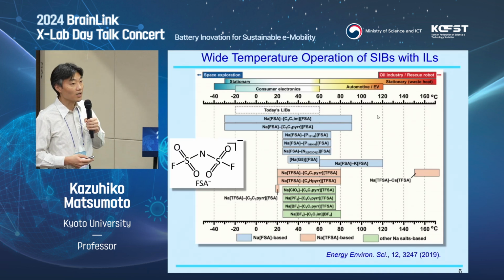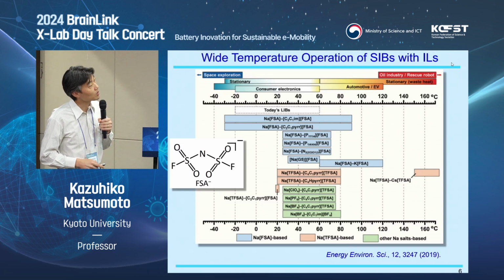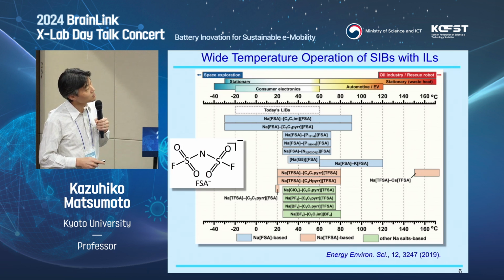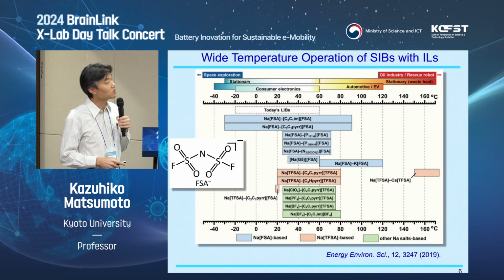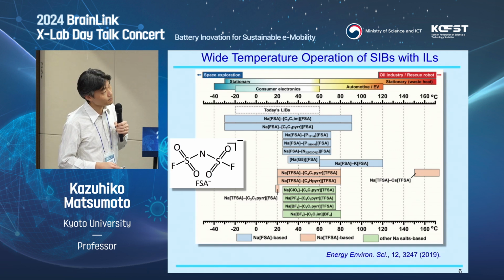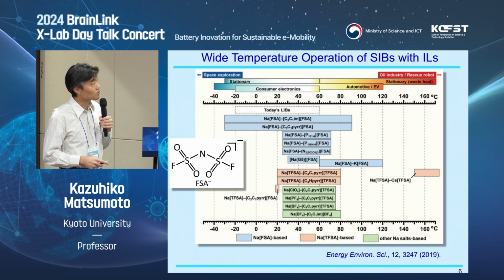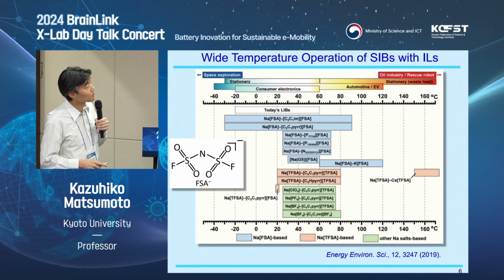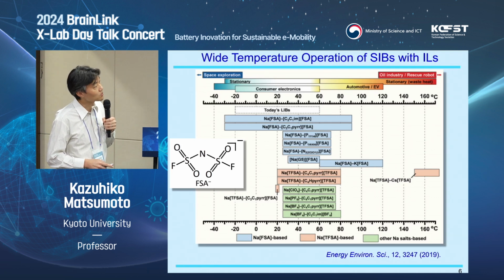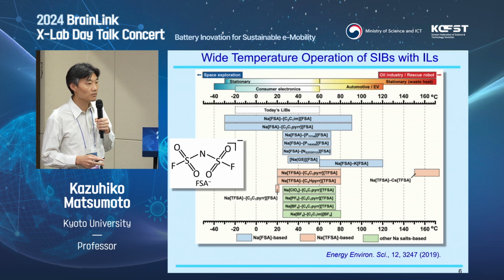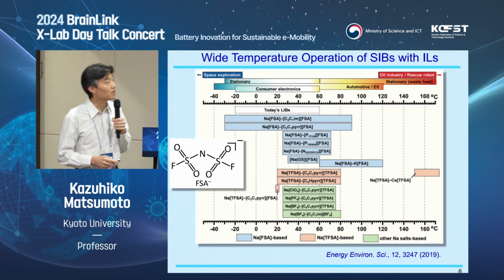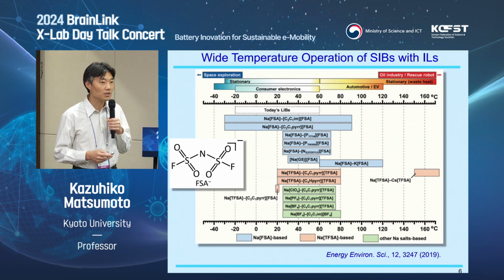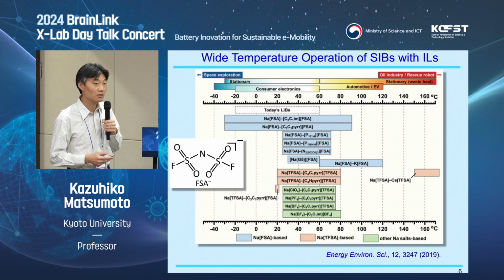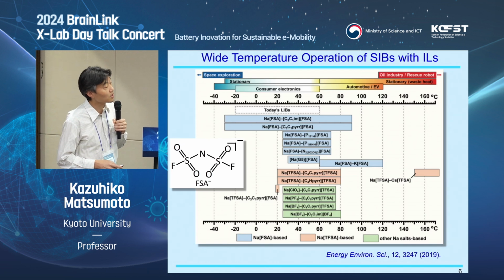Here, I'm showing a wide temperature operation of sodium-ion batteries with ionic liquids. So these are the typical applications at different temperatures. And we have some low temperature application and high temperature application. But today's lithium-ion batteries are usually operated between -20 up to 60 degrees C. The high temperature limit has several factors, but the important thing is the stability of SEI, the surface film on the negative electrode. So usually it breaks around this temperature, so we cannot go higher.